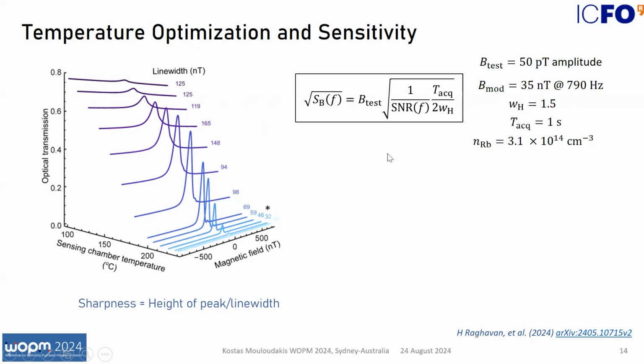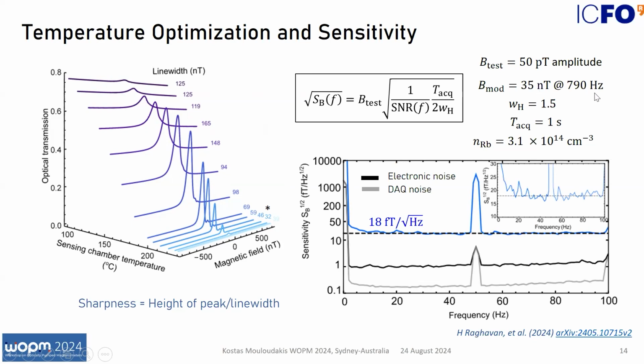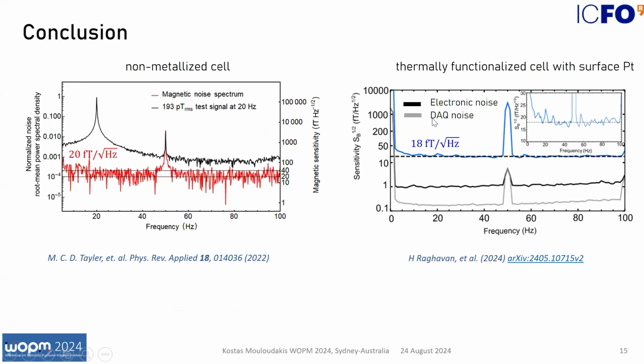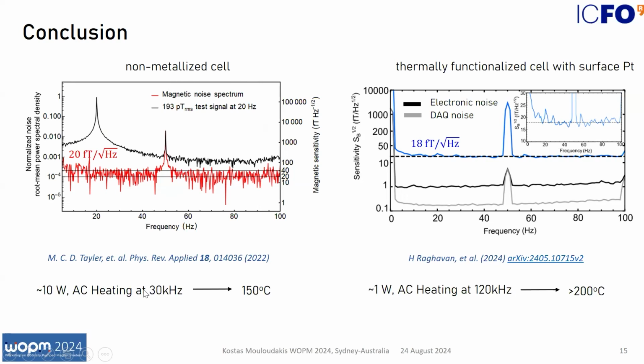After maximizing the temperature, we optimize the rest of the parameters of the magnetometer. We modulate at 790 Hertz with 35 nanotesla amplitude, and we obtain a sensitivity of 18 femtotesla per square root Hertz in the frequency range from 0 to 100 Hertz, which is relevant for MEG. To quantify the sensitivity, we use this formula here. Finally, we compare this sensitivity with the one we obtained in a previous publication, where we were using the same dual chamber vapor cell, but without the thermal functionalization, without the metallization on the glass. We were heating using a ceramic oven up to 150 C, and we obtained a sensitivity of 20 femtotesla. Therefore, we conclude from these two measurements that the thermal functionalization doesn't really add thermal magnetic noise to our system.